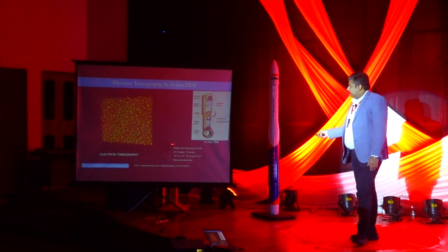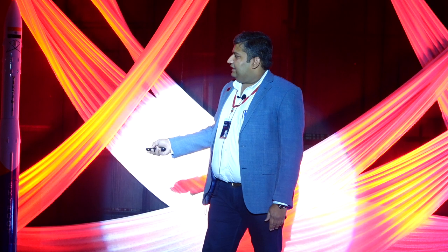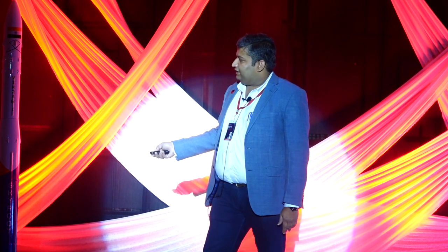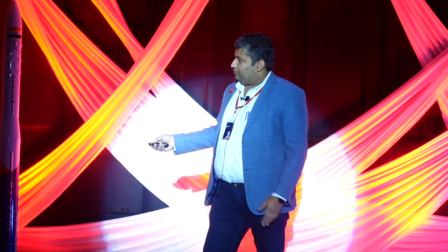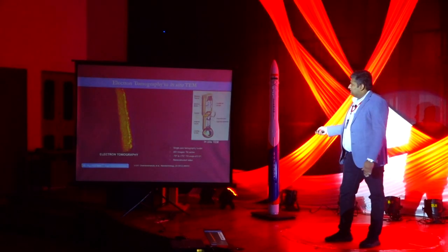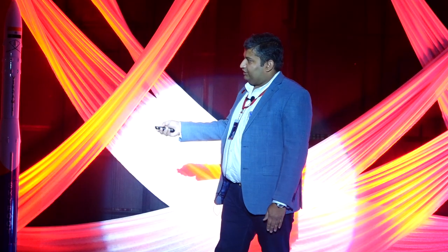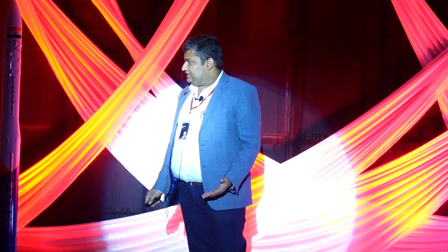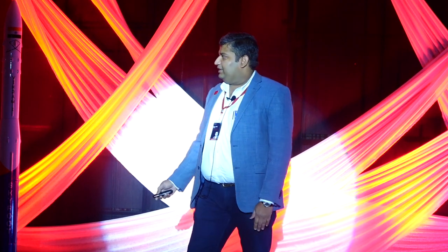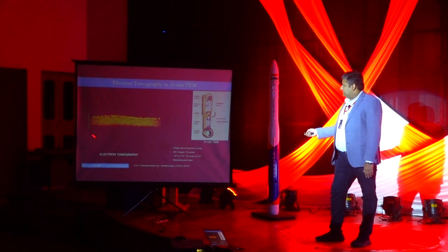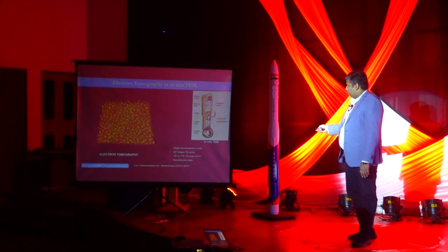By using a variety of techniques of tomography, we collected around 281 images, tilting the specimen holder and sample from minus 70 to plus 70 degrees and reconstructing the entire object. So what image or the video, whatever you see here, is a reconstructed image of 281 images, taking a lot of effort for that time. But through this, I was able to establish this in that laboratory there.